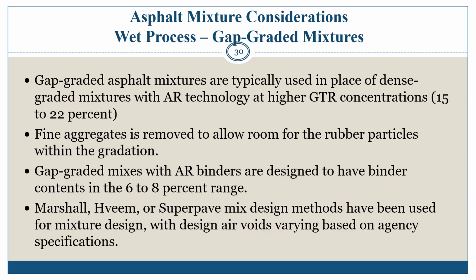Asphalt mixture considerations, wet process for gap graded mixtures. The three general mix design methods, Marshall, Hveem, and Superpave, have been used for gap graded mixture design. Gap graded mixtures are generally used with AR technology in place of dense graded mixtures. GTR concentrations may be in the 15 to 22% range. Gap grading generally consists of removing a portion of the fine aggregate to allow room for rubber particles within the gradation. Typical binder contents of gap graded mixtures are in the 6 to 8% range.